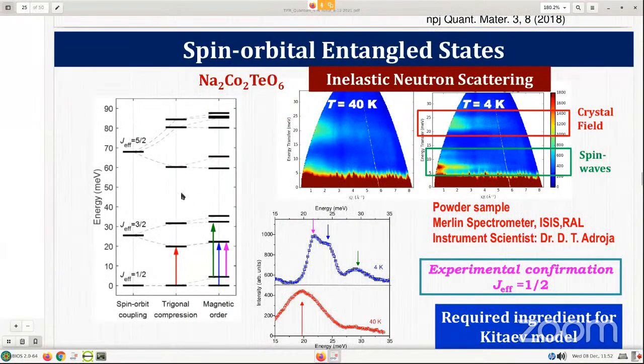We have also done the inelastic neutron study, and here is the J equal to half state under the trigonal compression. This is the crystal field state, and when magnetic ordering takes place, which indeed occurs for this system, again there is a splitting and there are 3 lines. What I am showing here by inelastic neutron scattering at 40 Kelvin, we see only this crystal field line, this red one. But when magnetic ordering takes place, in the inelastic study at 4 Kelvin, we do see all 3 transitions. There is a one-to-one color coding, green, blue, and magenta, for these 3 transition lines. These all are crystal field excitations.